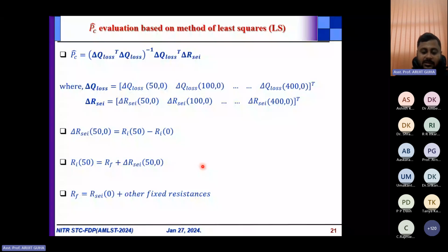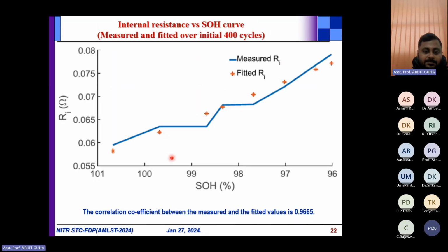This is the way that I have shown here. Delta R_sei, suppose this is 50, it is basically RI 50 minus RI 0. So the internal resistance at the 50th cycle minus the internal resistance at the 0th cycle. Now the internal resistance at the 50th cycle is basically the fixed resistance plus the delta R_sei. In this way it is computed. RF is basically some R_sei, which in the initial 0th cycle is basically 0. Here Q loss is basically the change in the capacity, which you can find out.